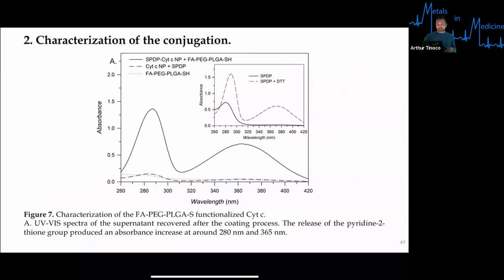So here we're looking at the characterization of the folic acid PEG PLGA thiofunctionalized cytochrome C. This UV-Vis spectra is of a supernatant that was recovered after the coating process. The release of the pyridine thione group produced an absorbance increase at around 280 nanometers, and also at 365 nanometers. So this is just an indication that you have the conjugation of interest that you want, and also the potential to use this as a way to track the release of the protein itself, the cytochrome C.